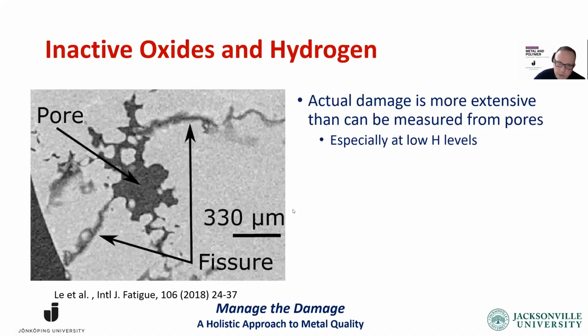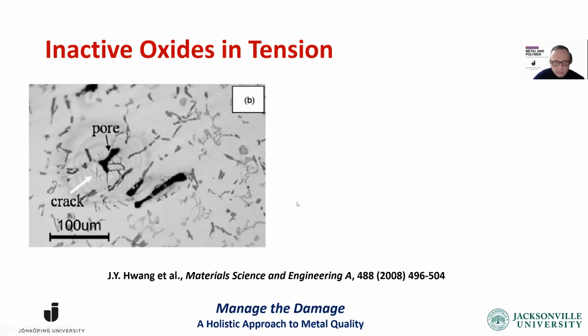So if we were to remove the oxygen, then we would remove these pores and we would basically hide them. What the damage cannot hide from is a tensile stress. So these inactive oxides open up in tension. Here's a picture from an in situ tensile test. You see a pore and you see all these cracks around it opening up just at very low stress levels.